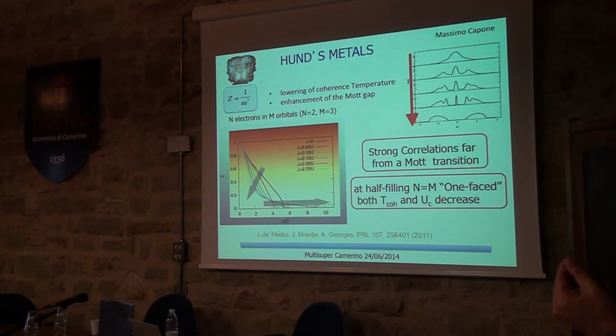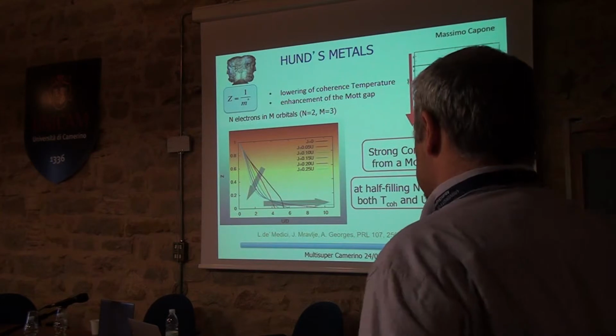This is the effect of the correlation, the reduction of the quasi-particle weight, the reduction of the coherent part, and this factor, usually called Z, goes to 0. So the spectral weight disappears at the Fermi level by shrinking. Of course, the spectral weight that goes away is moving towards high energy excitations, which we call the Hubbard bands. This is the standard scenario with no Hund's coupling, the single band Hubbard model. The Mott transition happens when Z goes to 0, which also means that the effective mass diverges. The system is no longer metallic because the carriers are infinitely heavy.